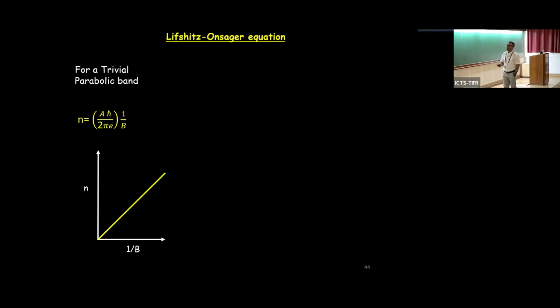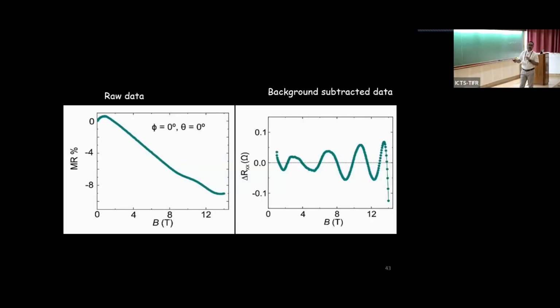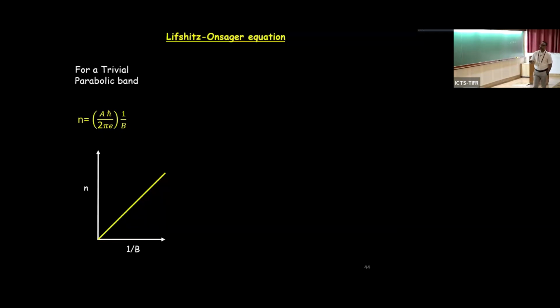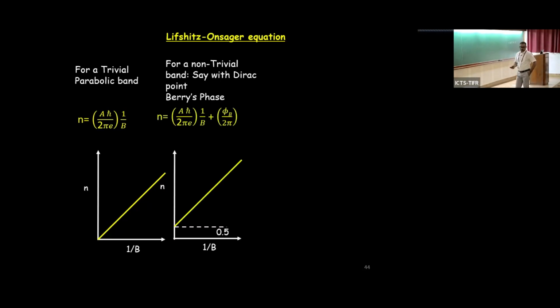the Lifshitz-Onsager equation. So this up point and down point, you can mark as a Landau index, which is n. Then this Landau index is inversely proportional to the applied magnetic field. So if you plot 1 over B versus n, it should be a straight line passing through the origin. But this is for a material where you have a parabolic band. Instead, if you have a linear band crossing, where the crossing point gives the idea of a magnetic monopole in momentum space, then in addition to this term, you must have a Berry phase term.